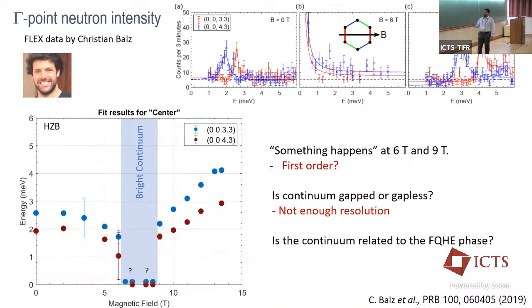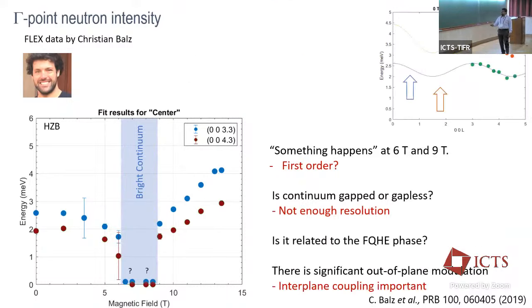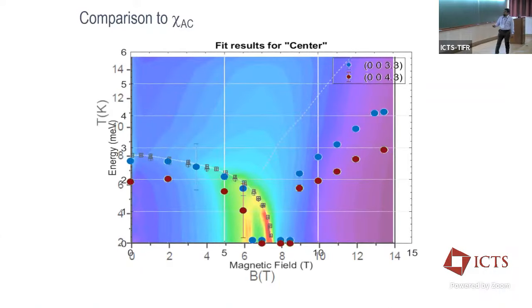And then Christian Balz measured data at FLEXX all the way up to 18 Tesla. What he figured out is that you see magnon modes at 0 Tesla, and at 13.5 Tesla you also see the magnon modes. But close to 8 Tesla is where he saw this bright continuum. He was not able to say whether these are gapped or gapless, but that's what he could measure. If he superposed that data on top of the AC susceptibility data, we find that this is where you start to see the bright continuum, where you start to see this other zigzag phase. And then here, you also see the bright continuum, which spills beyond all the zigzag phases. So that tells you what the whole phase diagram looks like.